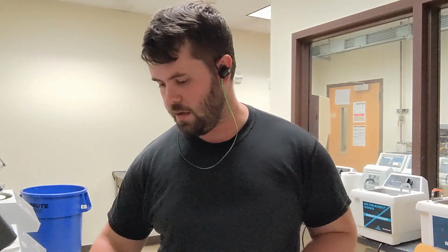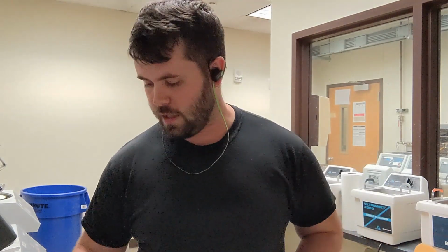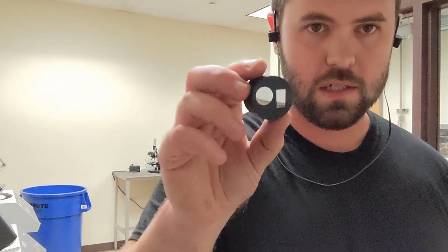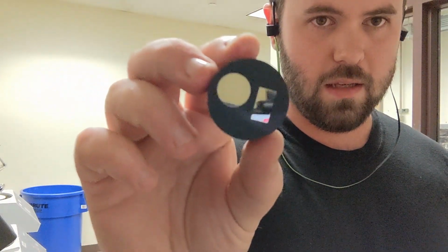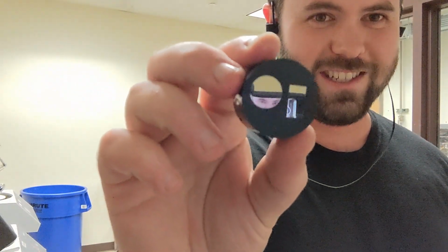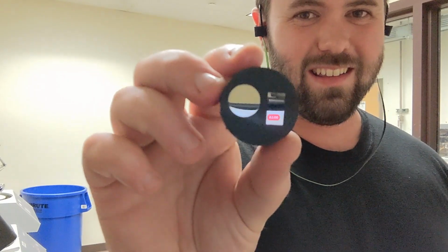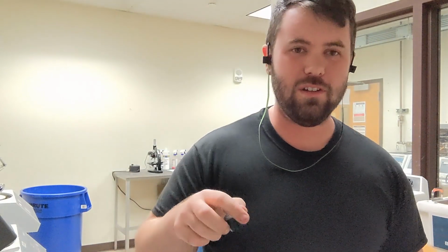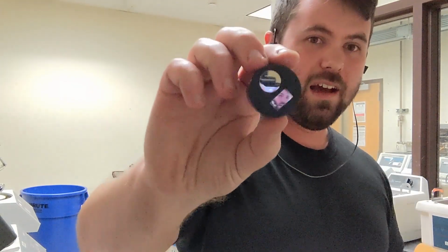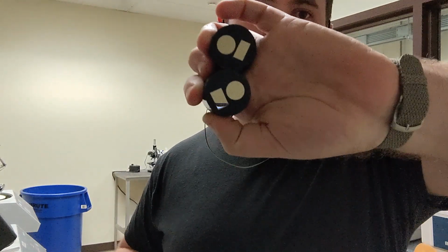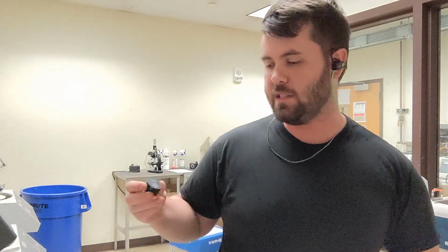All right, so we've gone through the first 2 polishing auto polishers, and our cross sections now look like this. If you see, you can actually see the reflection in the camera of the surfaces. So we have a pretty much a near mirror finish on our samples, which is really, really nice. We have 1 polishing step left. That is the 0.3 micron.